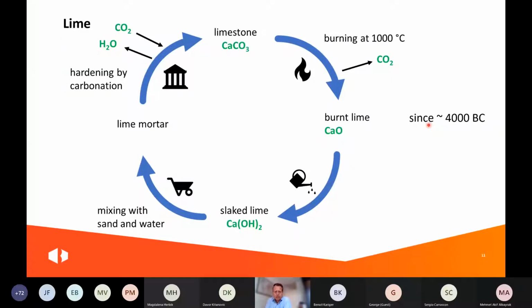Then around 4000 before Christ, lime was invented, probably by the Egyptians, but you will also find other possibilities. But this was, of course, a huge step forward. And lime itself is quite a circular product, as you can see here. You start with limestone, which is found in nature. You burn it at 1000 degrees. Then you get burnt lime, and you combine it with water. And then the slaked lime you can use to make a mortar with sand and start building, or coat the adobe, as also happened.